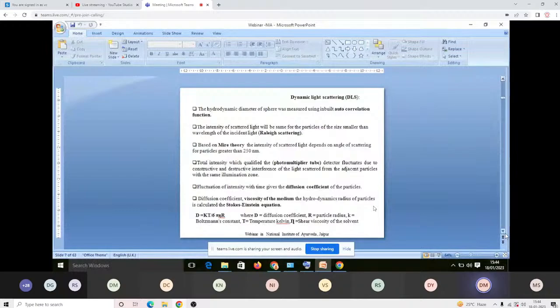Actually, briefly, when the particles are in aqueous media, they undergo random motion, and with the laser light there is constructive and destructive interference between two adjacent particles, and that gives the total intensity with the help of the Stokes-Einstein equation, where D is equal to kT by 6 pi eta R. D is the diffusion coefficient, R is the particle radius, k is Boltzmann's constant, T is temperature, and eta is the shear viscosity. This is the viscosity of the solvent.